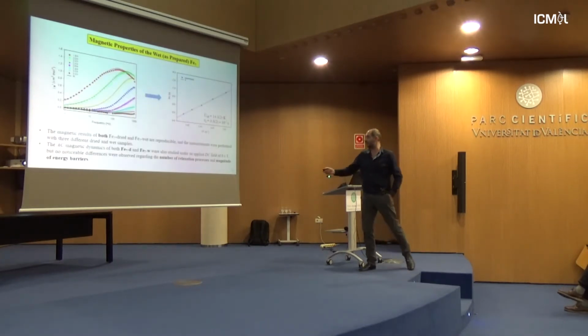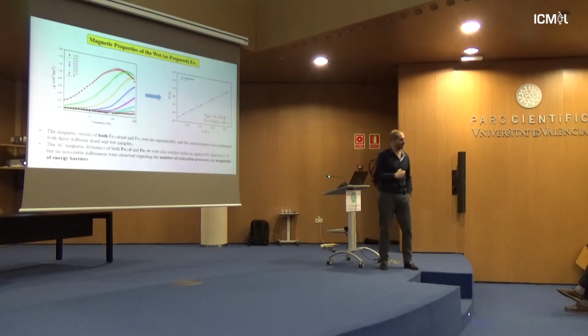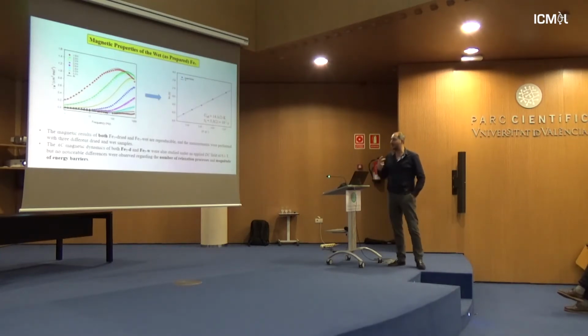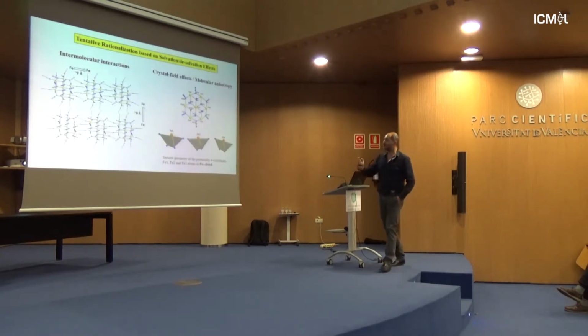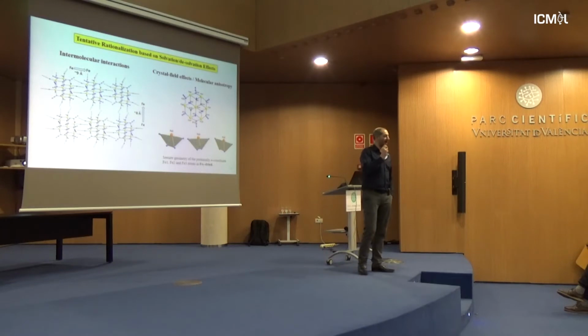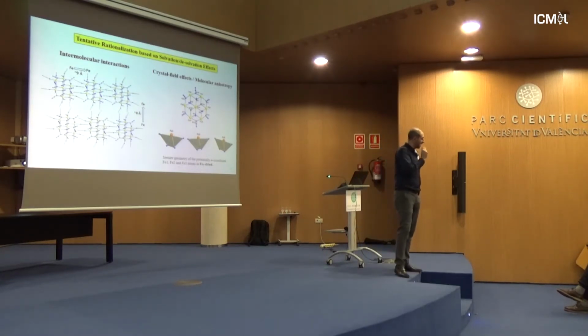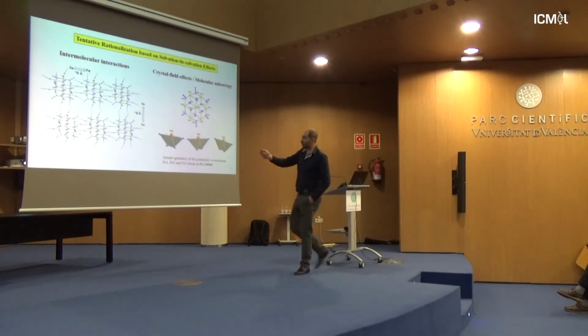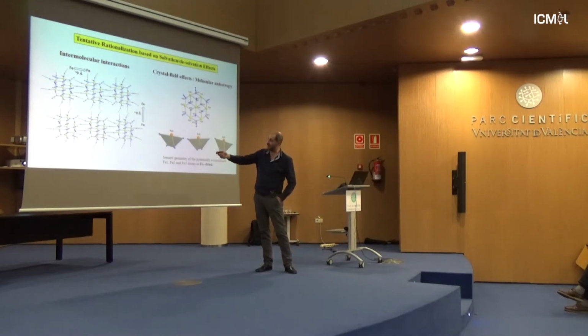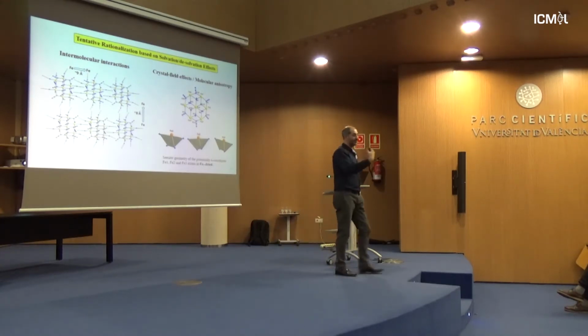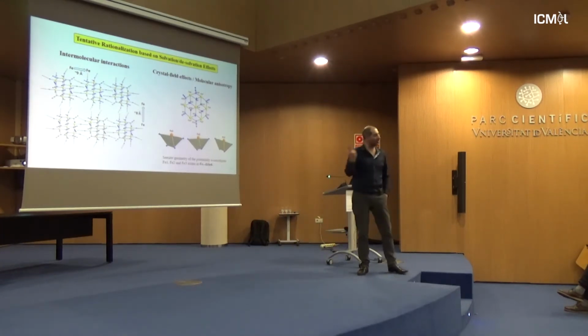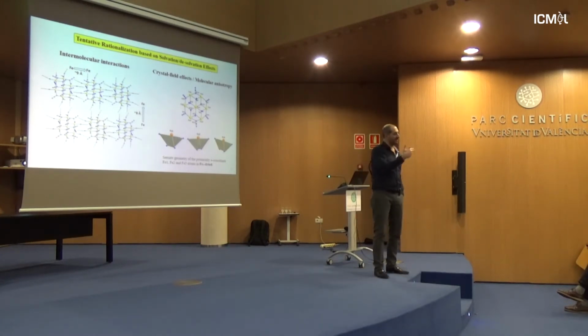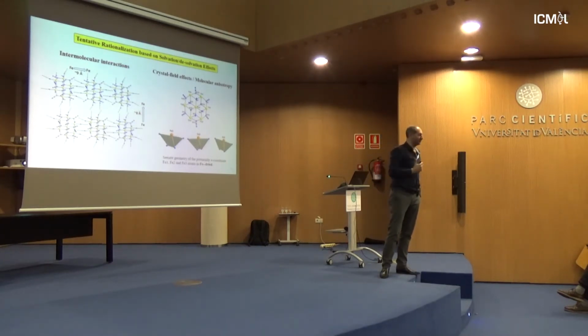So what we really believe, excuse me, I forgot to mention that this has a 14 Kelvin energy barrier, but this is not the important part here, is to understand and explain what's going on. So we believe that we have a large contribution of the intermolecular interactions which contribute to the onset of the high temperature energy barrier. We believe that in the dried compound, those acetonitrile molecules are completely removed. Then the molecules get closer to each other, and you start having interactions between the clusters within the crystal lattice. So that's option number one.